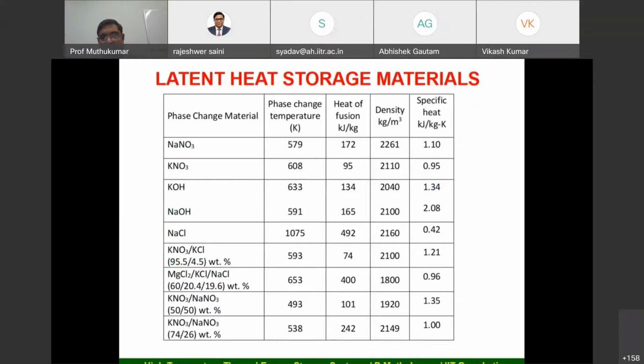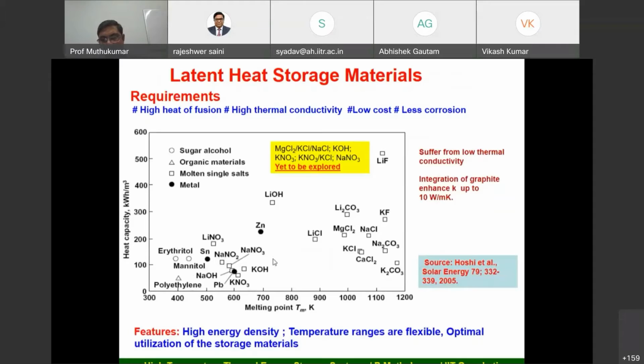1000 PCMs are available for storing heat in the range of about 50 up to about 700, 800 degrees Celsius. Here, actually, these materials are tailor-made, I can say, according to your requirement and temperature range. You can tailor the material. Tailor means, for example, now you see here KNO3 and KCl, here 95.5% KNO3 and 4.5% KCl. If you vary the percentage, then obviously the melting temperature and the phase change enthalpy will vary. So you can fine-tune the composition according to your requirement.